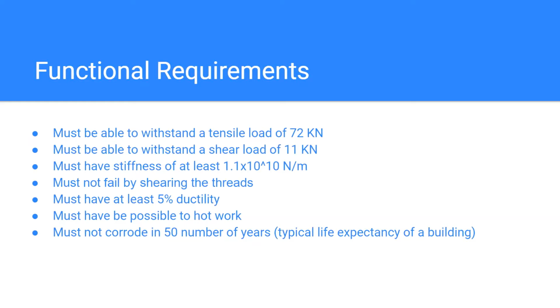Using the actual bolt's diameter of 1 inch and nut height of half an inch, it was determined that the bolt would fail from tension at a lower force than the force causing the threads to shear off. Using the approximation that strength in shear is 0.6 of that in tension, it was determined that the bolt would fail in tension before it would shear. Thus, the shear and thread shear requirements can be reduced to one requirement that the bolt be able to withstand 71.667 kilonewtons in tension with a safety factor of 2.